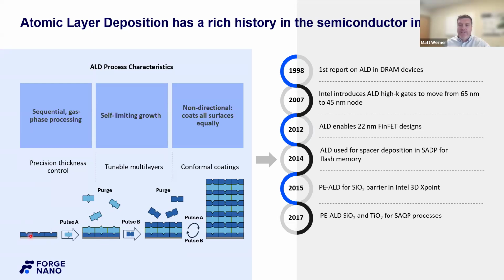So just walking from left to right, we have a surface that has some reactive site. That's this blue divot. We then introduce a precursor. That precursor has a complementary reactive site. That's this light blue spike. Those spikes meet the divots and you fill the whole surface up. You get one single monolayer, and then the reactions cease. The spikes don't react with the spikes. So you can put as much of these blue spiky precursors in as you want, and you will not get any further reaction, no more than this monolayer.